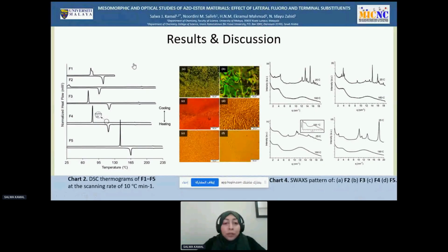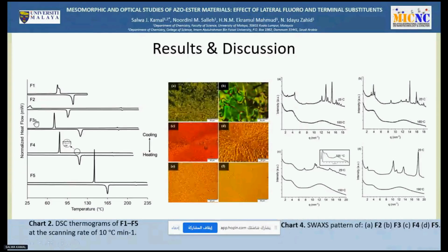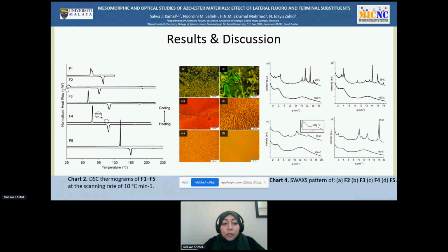The mesomorphic properties were studied by DSC, POM, and SWAX. As you can see in the DSC thermograms, the unsubstituted terminal compound F1 showed only one transition peak, from crystal to liquid, without a trace of liquid crystalline phase, while compounds F2 and F3, with methoxy and butoxy terminal substituents, showed two transition peaks, from crystal to nematic phase, then from nematic phase to isotropic phase, with grainy and schlieren texture respectively, while compound F4 with the bromo terminal substituent showed three